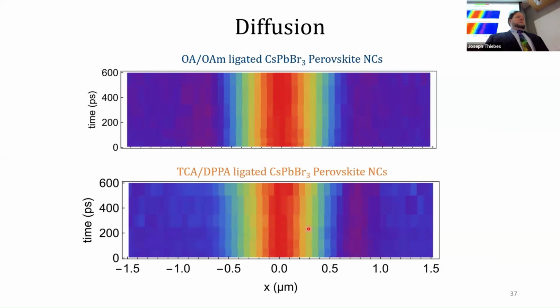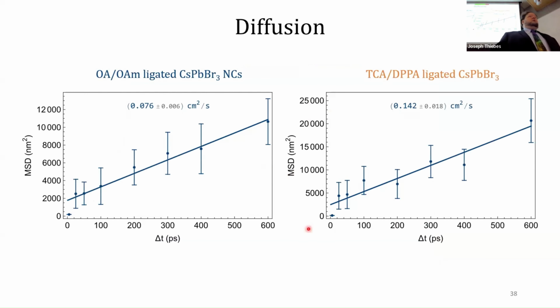And so I did some other analysis. This is maybe a qualitative view of it, but if we plot the mean squared width of those Gaussian functions, we can see the width of them increasing roughly linearly over time. And then we can get the slope of this line, and that's proportional to the diffusion coefficient. For the oleic acid oleylamine one, it's this number, which doesn't mean a lot out of context. But if you look at it in comparison to the conjugated ligand, it's about twice as big. So we're basically seeing diffusion in this particular example that's about twice as fast as in the original prototypical system.